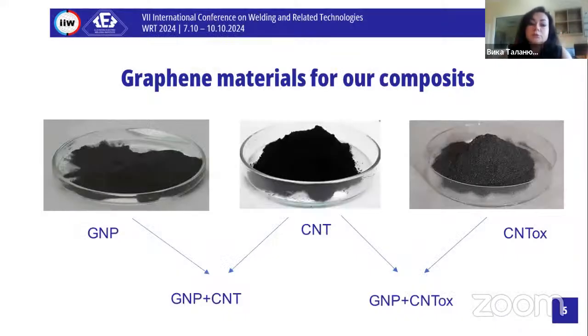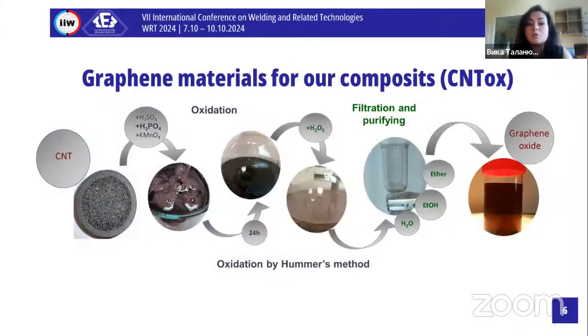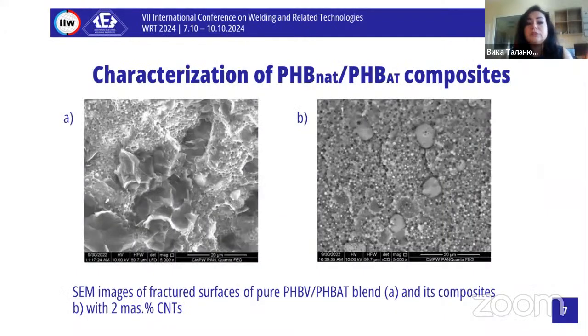What kind of fillers did we use? We used graphene: GNP, CNT, and CNTox. After the functionalization, we change the concentration of these materials and get some proportions of GNP and CNT, and GNP and CNTox. Our functionalization of CNT to get CNTox is an oxidation by the Hummers method. We get it in our laboratory in the synthesis process. And here you can see some results of our measurements.